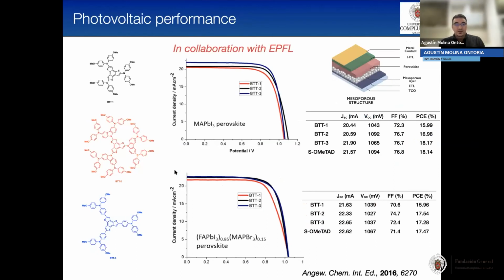These hole transporting materials were combined with 2 different perovskites, with the methylammonium lead iodide that I said is the most common one, displaying efficiencies very close to those reported by the reference compound, the spiro-OMeTAD. In the case of BTT1, it was lower than that. If we see the mixed cation, mixed anion perovskite, which is this one, they are also showing excellent performance close to that of Spiro. Again, the lower efficiency was obtained for BTT1. And why is that? Because the solubility was a big issue for this molecule. It was very difficult to dissolve, and for that the film forming ability was much lower than the other 2.